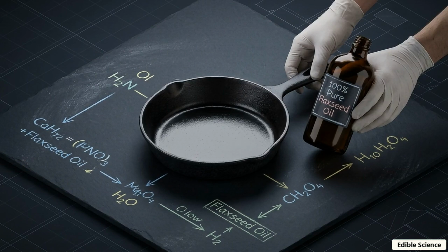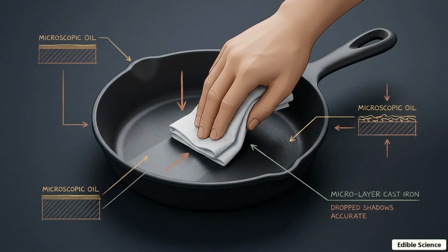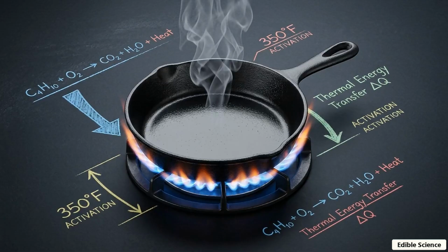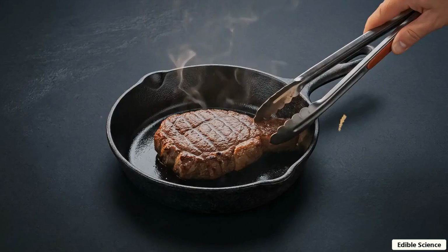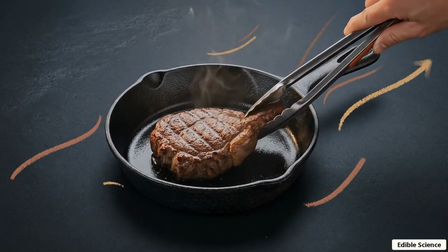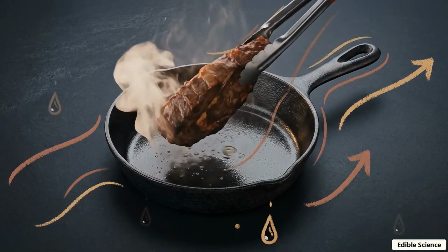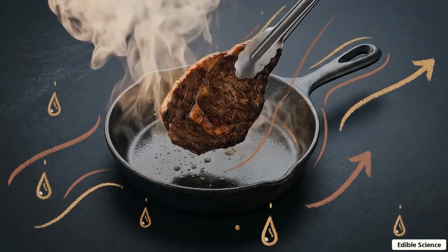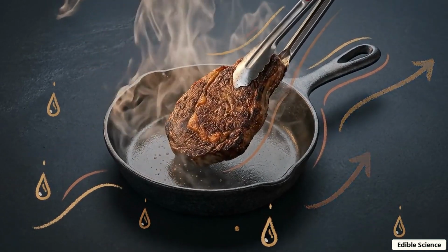Success depends on a specific formula. Bake an oil high in polyunsaturation, apply micro-thin coats to allow oxygen permeation, and push past the smoke point to trigger the radicals. A flawless skillet is the physical byproduct of a patient, repeatable material science experiment. It's a high-temperature polymer reactor producing dinner as a byproduct.